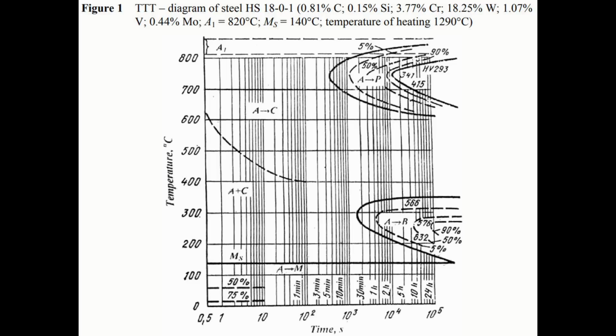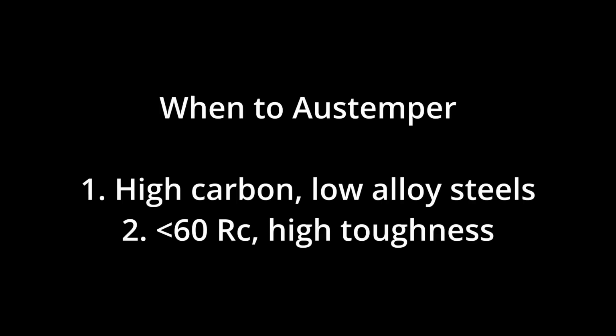So high alloy tool steels, they don't usually have issues with plate martensite. The transformation times are extremely long, and so I think Austempering is not really well suited for these types of steels. So in which cases should we use Austempering? I think Austempering is really great for high carbon steels. So we'll say 80, 85 points of carbon and above, and a relatively low alloy content.